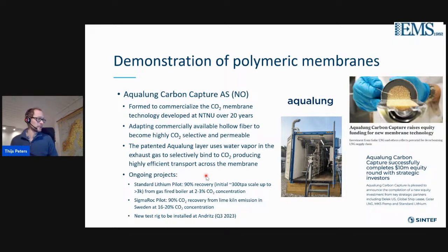At the moment in Sweden, they have a pilot plant also capturing 90% CO2 from a lime kiln emission, which is a much higher CO2 concentration of 16 to 20%. And recently, they also announced a cooperation with Andritz, where a new test rig will be installed.